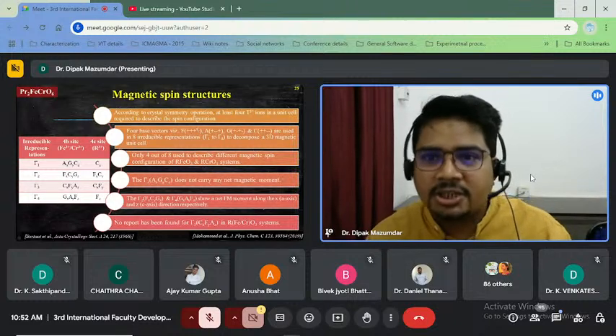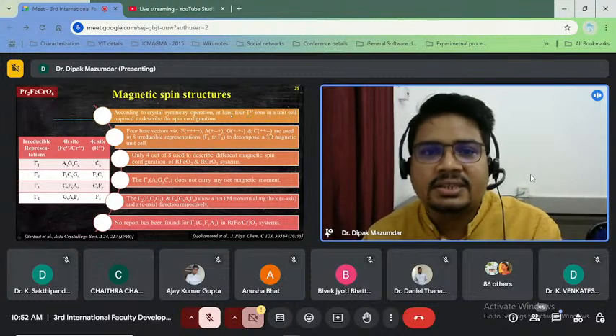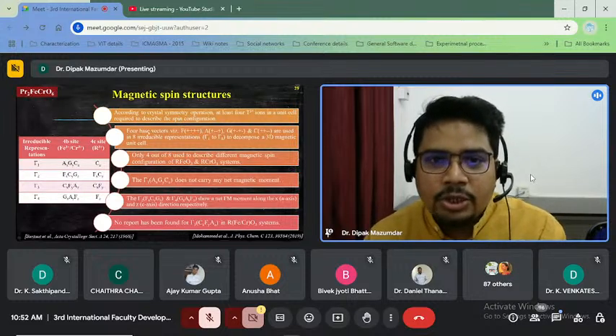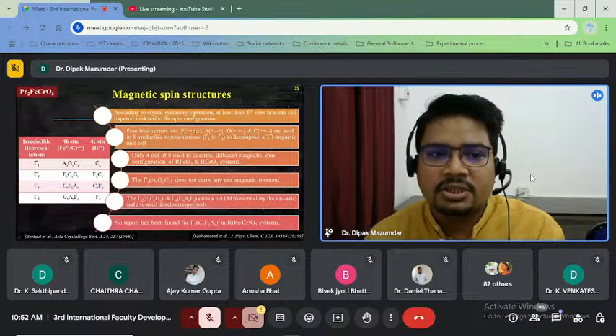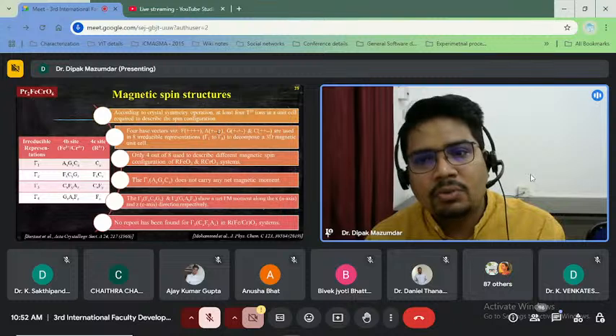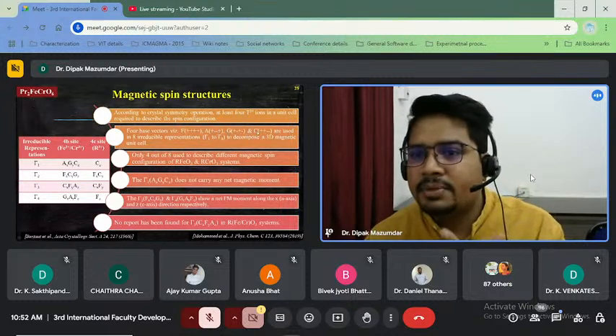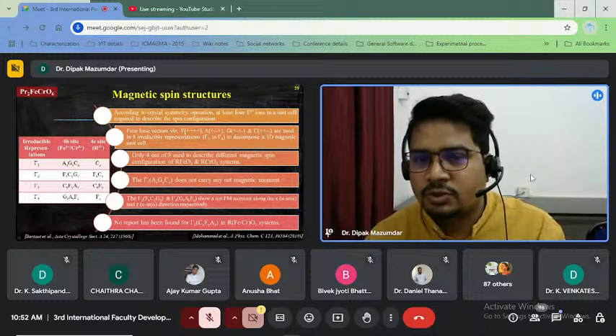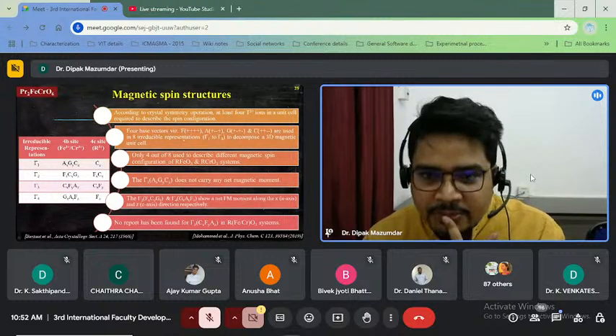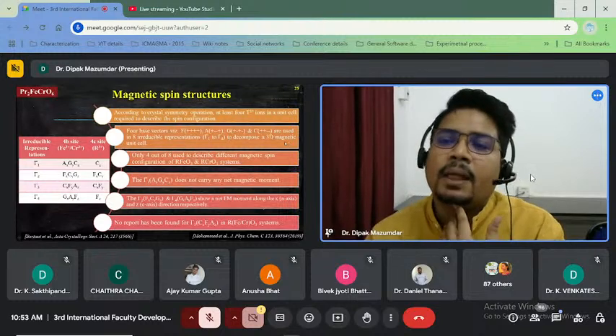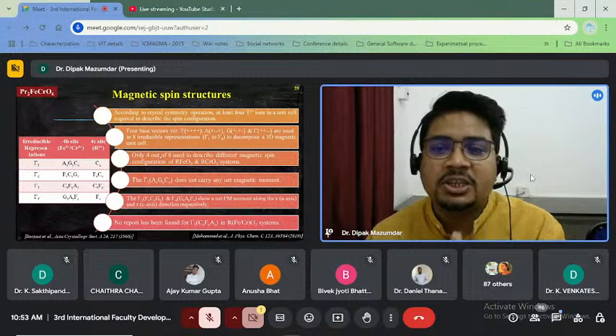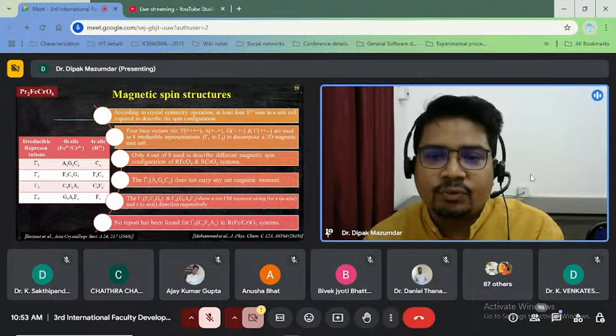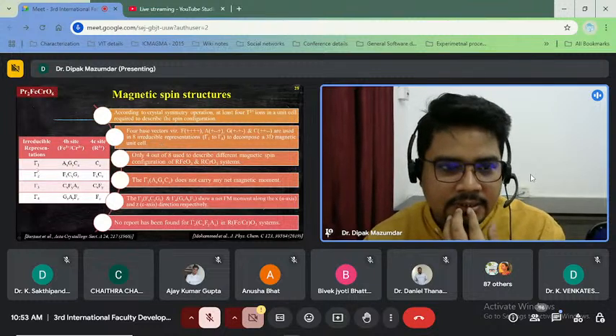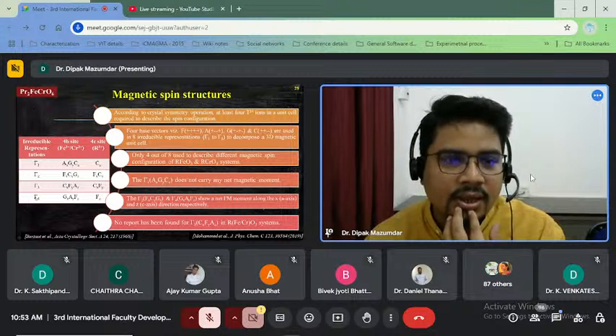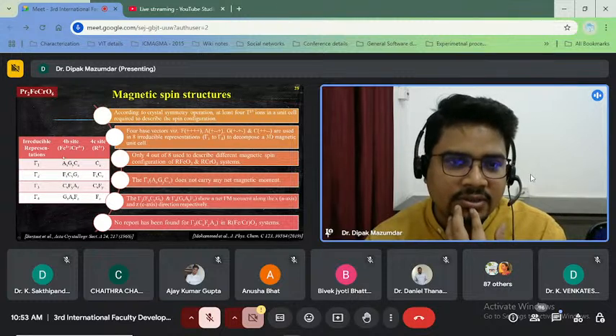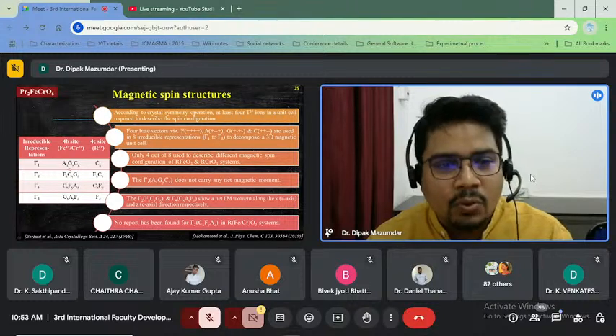So according to the crystal symmetry, at least 4 transition ions in a unit cell are required to describe the spin configuration. And there we use 4 base vectors: F, all plus, which represents ferromagnetism; A, up, down, down, up; again G, up, down, which I already told; and C type. So these 3 represent antiferromagnets, and this is the only ferromagnet. These are used in 8 irreducible representations from gamma 1 to gamma 8 to decompose a 3D magnetic unit cell. But out of these 8, only 4 are utilized to design the magnetic spin structure of the ReFeO3 and ReCrO3 systems. So here you can see the 4 irreducible representations, gamma 1, gamma 2, gamma 3, etc. And this orientation represents the 4b site, how the magnetic spins or the atoms will be oriented.